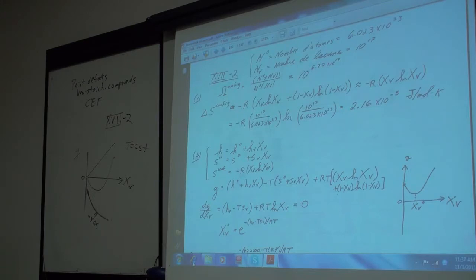It's a thermally activated process. It goes up exponentially with the temperature. So at room temperature, the number of vacancies is extremely small, but it's going up exponentially. So when you get up to a metal at 1,000, 1,200, 1,300 degrees, you can have a fairly appreciable number of vacancies, 100 parts per million, that sort of thing. Not negligible. And these, of course, affect the thermodynamic properties slightly to some extent, but they certainly affect the transport properties. This definitely affects the diffusion.